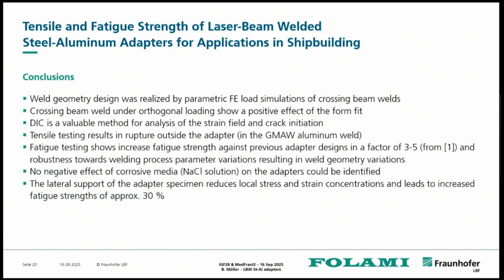We have seen that digital image correlation is quite a valuable method for the analysis of the local strain field and then for crack initiation as well. Under tensile testing, there was not so much information on the cracks of such an adapter, since the final rupture was in the aluminum weld outside. However, under fatigue testing, the root notch between the sheets led to a fatigue failure. We showed that a factor of 3 to 5 towards previous designs is realizable, and that it is quite a stable adapter towards welding process parameter variations.